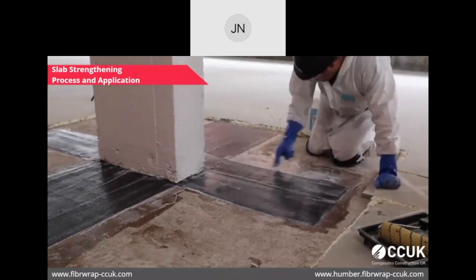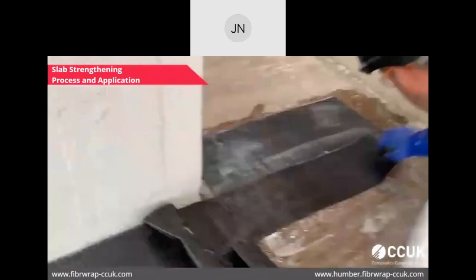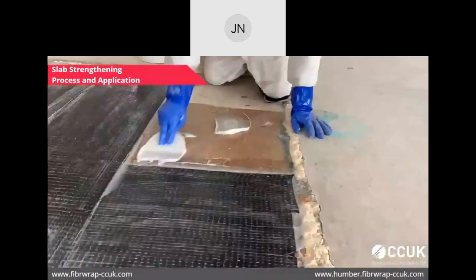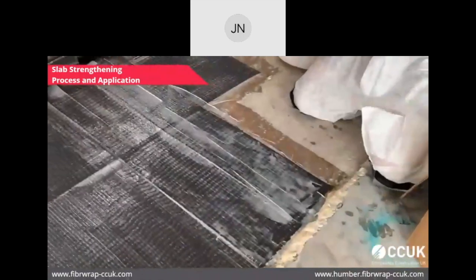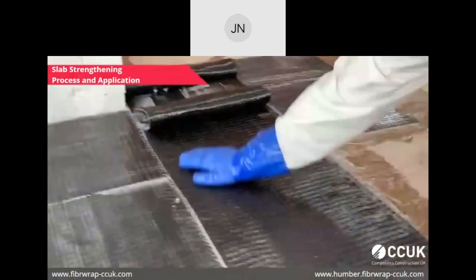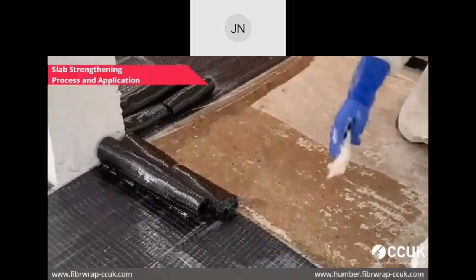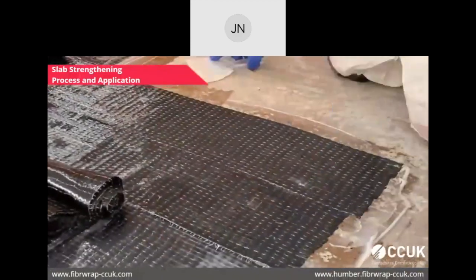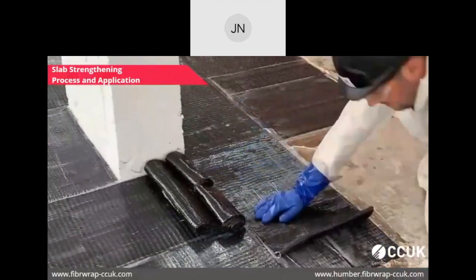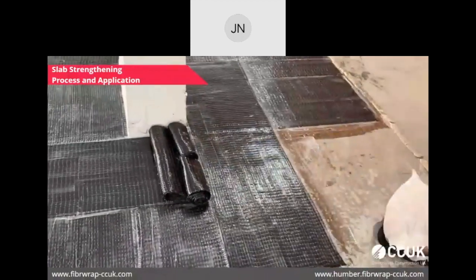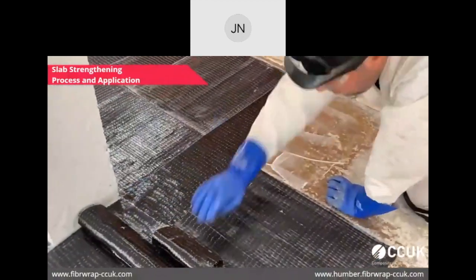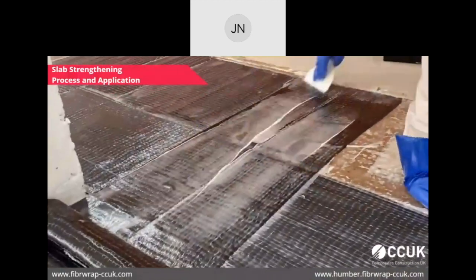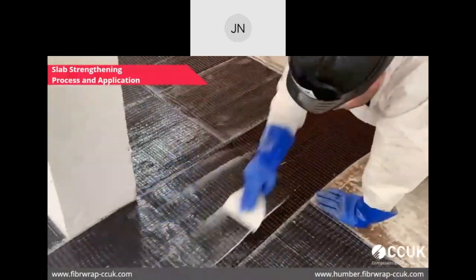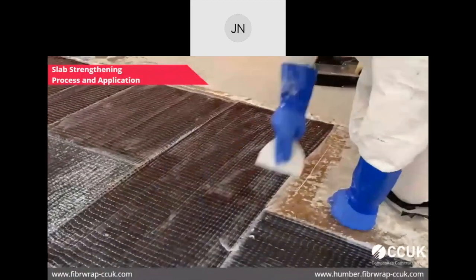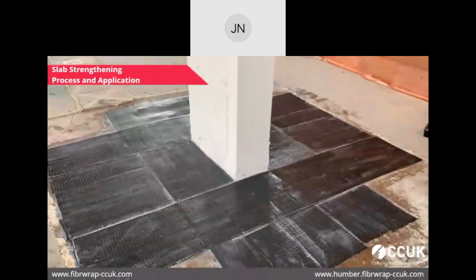And then once you unroll it, you just squeeze out the additional epoxy, put another coat of epoxy on top of it, and then you keep on following until you put the number of layers required as per the design. So once that is done, you can leave this area to cure, or if it is in an environment like a waterfront or a chemical environment, you put a protective coating on top of it if required. Otherwise, you can leave it exposed like this, and once it is cured, you can plaster it, paint it, render it. You can do anything on top of it.